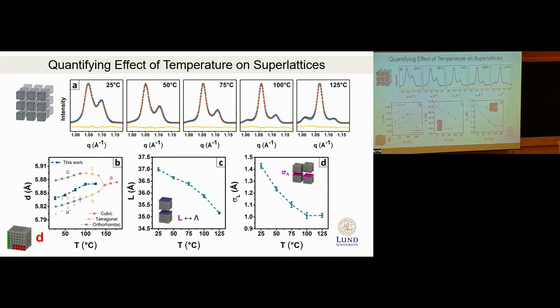By applying the model, we can obtain the following picture of the changes. First, since we can fit d, we can see that the lattice constant of nanocrystals is expanding as we heat the sample, which is consistent with expectation. Because perovskite nanocrystals at room temperature, when they are big, about 10 nanometers, are orthorhombic. As you start heating them, they change their structure to tetragonal, eventually becoming cubic. So the lattice constant expands. We can see this and then compare with literature, with a consistent result.